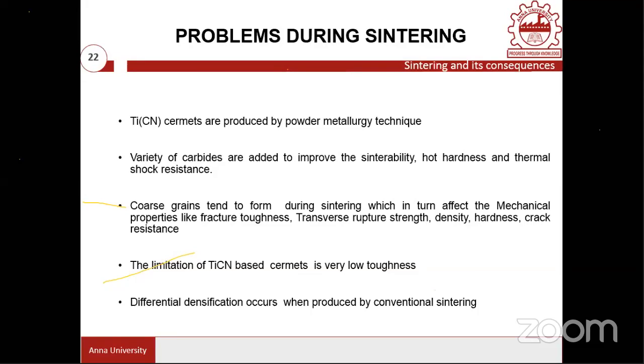And also there will be differential densification. At the outer side, the densification would be better, and at the inner core side, the densification will be very poor. That means it is something like a non-sintered center, while at the outer side you have a completely sintered component. So the densification won't be uniform in the case of a conventional material.